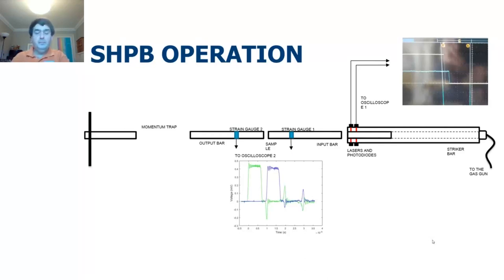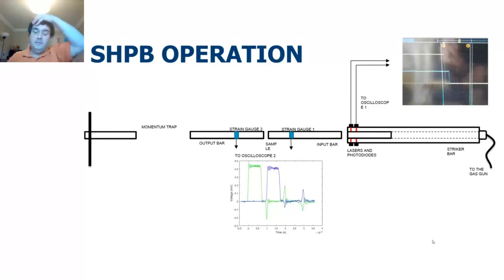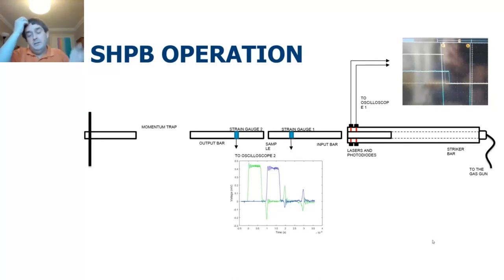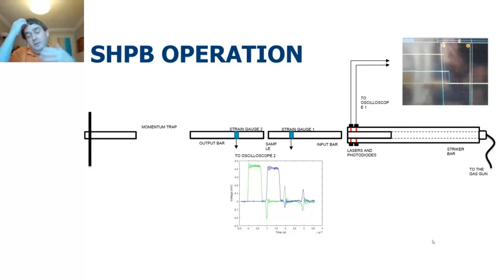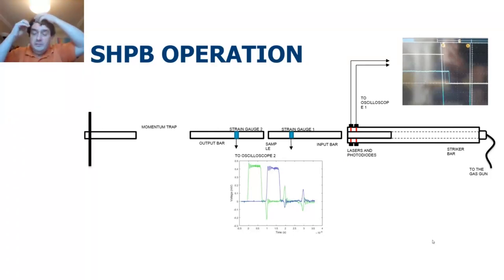Remember, we are not shattering the sample — we're only tapping it and increasing velocity until it finally breaks, so we expect fairly good transmission of stress. If we keep the sample intact, stress transmission is a form of measure of damage, because the amount of energy transmitted implies that energy has gone through the sample. If we were causing damage inside the sample that takes energy — that energy expresses itself in deforming or fracturing the structure. Good energy transmission generally means the material is not damaged.